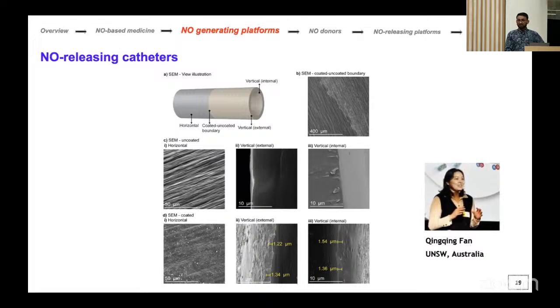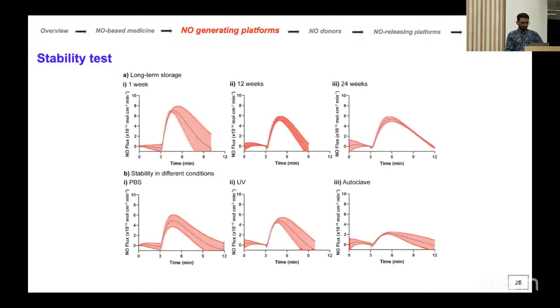And using scanning electron microscopy, we show that the material has been successfully conjugated, and we also look at the coating thickness. And then, because these devices are generally stored over the long term, we also want to see whether, if we store this device at room temperature, the NO generation ability will still be practically possible, and whether it will be clinically therapeutically relevant or not.